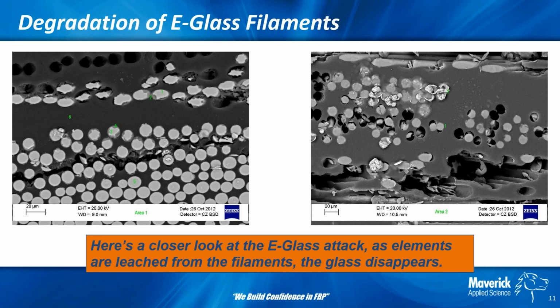It's being attacked. What we find is that some of the elements get leached out of the glass and start to break it down. And then you can see where crevices between the glasses are starting to occur. Further down, these are largely more unaffected parts as well. On the right-hand side of the slide here, you can see more of where the glass has been attacked or completely degraded, and then you can see a close-up of the cracks that are beginning to form throughout the resin matrix area.